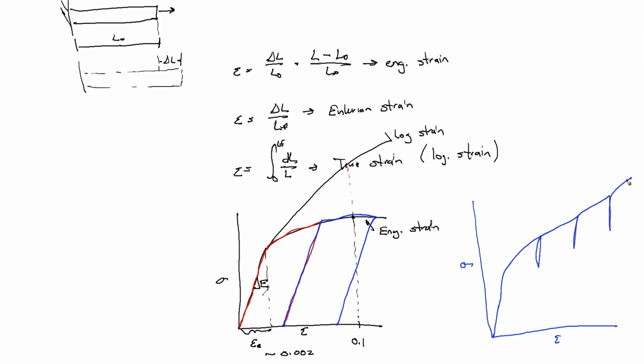It's exactly what they're doing is unload-reload, unload-reload, unload-reload, to get the elastic modulus. So then you can come back and you can fit straight lines to these guys to get the elastic modulus because it's very difficult to get right there. The elastic part of the curve is so small. I mean, I didn't draw it well. It should always be roughly the same slope.